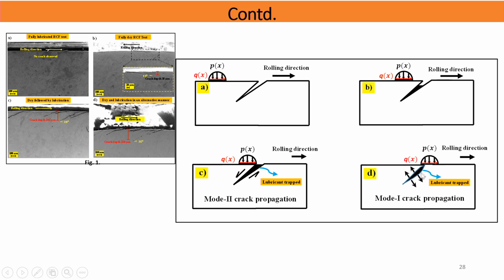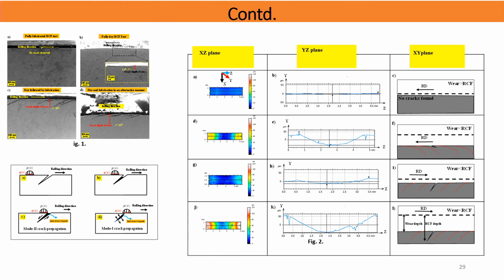And then when it rolls over the crack, especially for lubricated tracks or tracks having water or liquid in them, the hydrostatic pressure of this liquid gives you a mode 1. It creates a hydrostatic pressure, and so this crack will now propagate because of it. This is a problem with rail tracks. You will have cracks propagating because of this also. So to prevent this, what are the solutions? That is the important thing, because we were in touch with Indian Railways on this. I'll tell you about that.